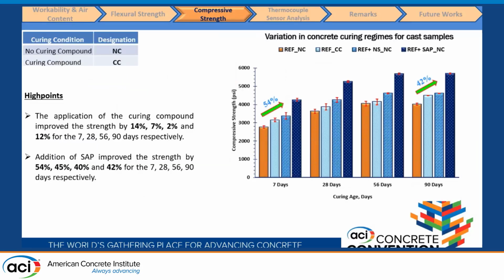We also tried to evaluate the performance of the concrete mixtures under different curing regimes. Here, the NC signifies no curing compound, and the CC signifies the curing compound. And we were able to evaluate the different mixes with a curing compound against those with internal curing, that is, superabsorbent polymers. We found that the addition of curing compound increased the compressive strength by 14% at 7 days and 12% at 90 days. But the addition of SAP increased the compressive strength by 54% at 7 days and as high as 42% at 90 days.